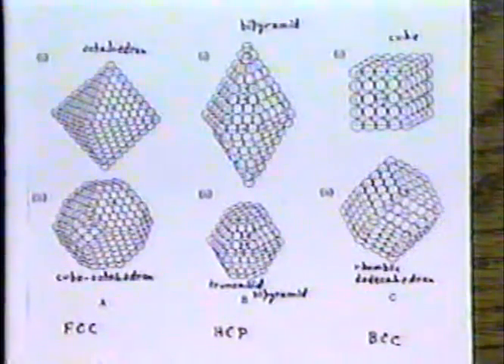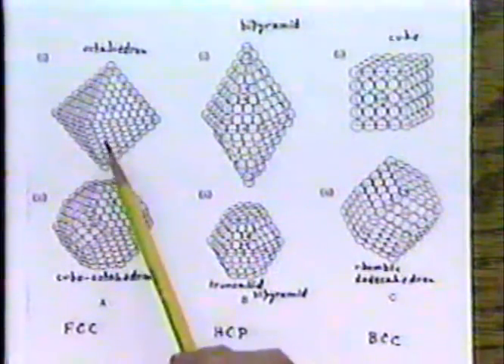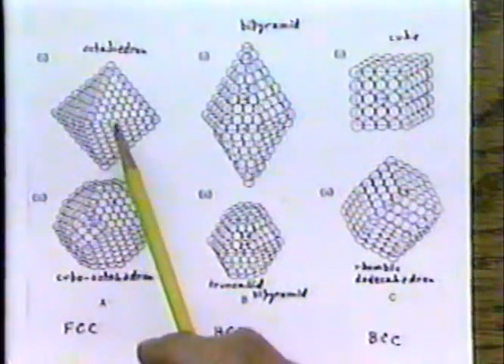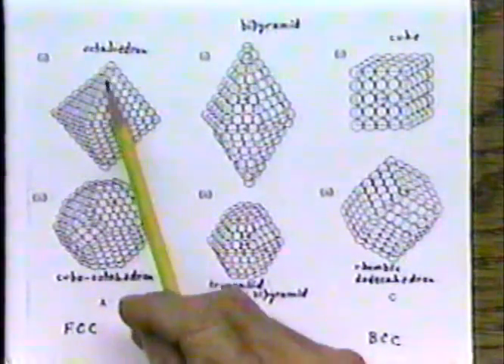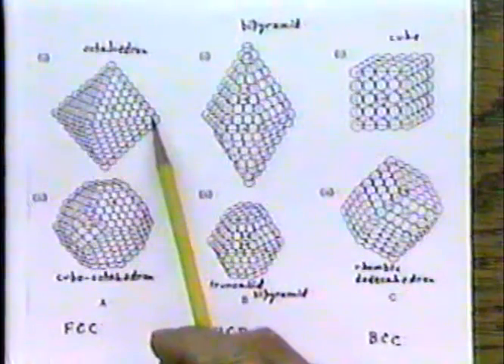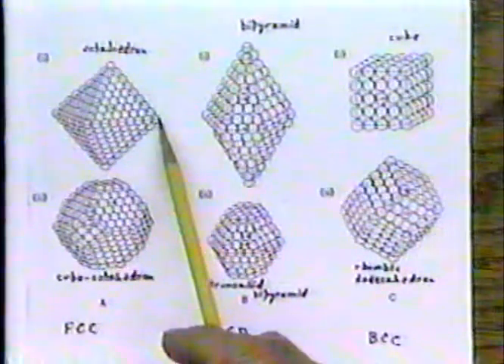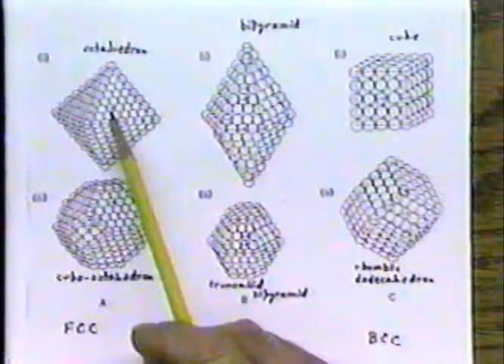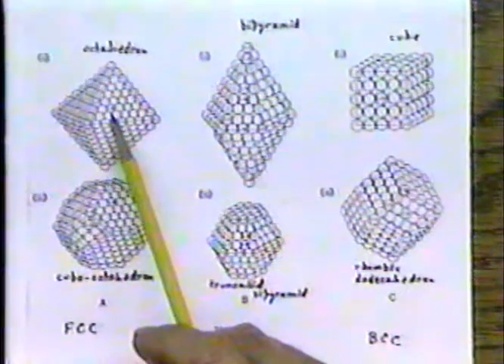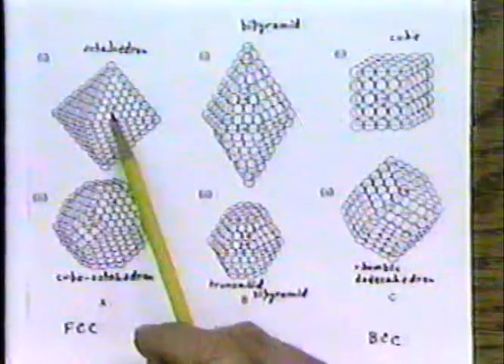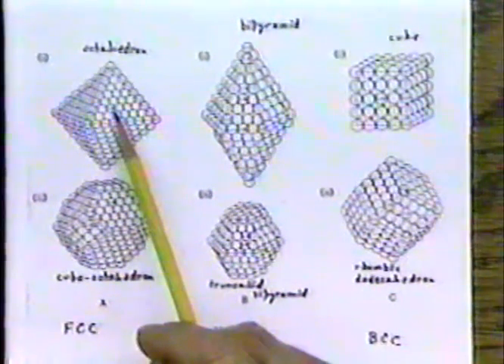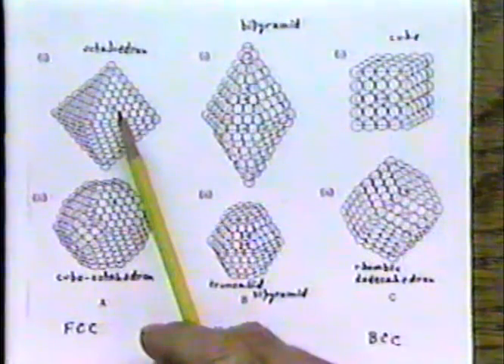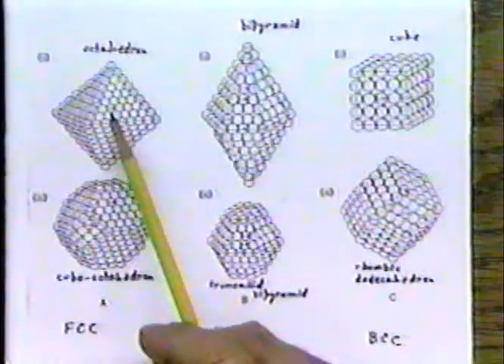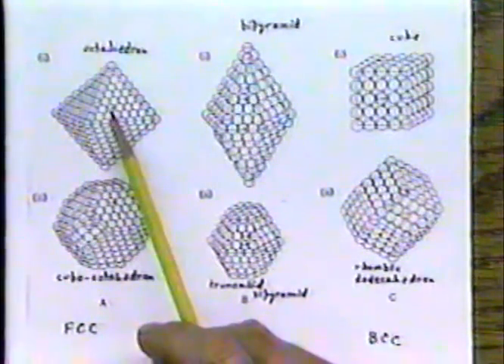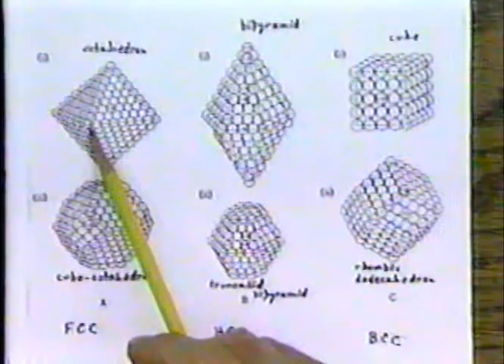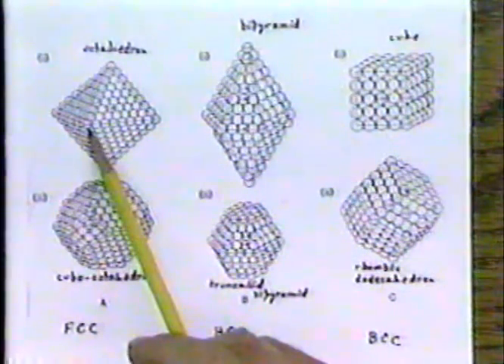To take this octahedral shaped particle over here, this is for a face-centered cubic system. Note that each of the faces on the octahedron is a 111. There's a 111 metal surface. In a 111 metal surface, the atom in the surface plane has 9 nearest neighbors. There's 6 in the plane itself and 3 below. That means, in fact, that it's lost 3 nearest neighbors in becoming a surface, because an atom buried in the center of a face-centered cubic metal has 12 nearest neighbors. But anyway, there are 9 nearest neighbors, whereas at a corner position out here, the atom only has 4 nearest